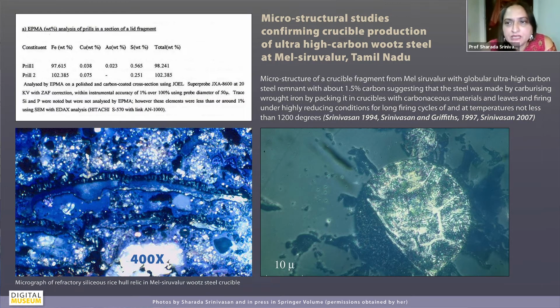What I had done was to look at the microstructural studies of a fragment of the crucible. And you see these trapped prills, which are basically globules of the metal that was prepared in these crucibles. You can see that the microstructure is what we call a typical ultra high carbon steel, hypereutectoid steel as it's called, because you can see the dark pearlite network, and then there is this honeycomb-like structure of the white cementite. When you look at that, you also understand how it resulted in the structure of the Damascus blades, because when you forge this extensively and then etch it, you get this light and dark pattern of the pearlite and the cementite.